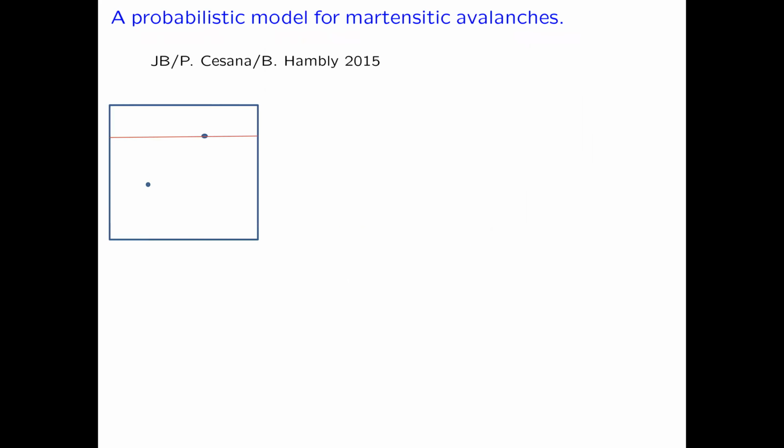And I think the martensite variants are just not so. So you were saying that not this one? Yeah, this one. So the thing is that there's two. You take the identity. There are two matrices on each well, which is okay, connected to the identity. But there are no rank-1 connections between those 12 matrices. That's the thing. So these interfaces that you're seeing are highly stressed interfaces.